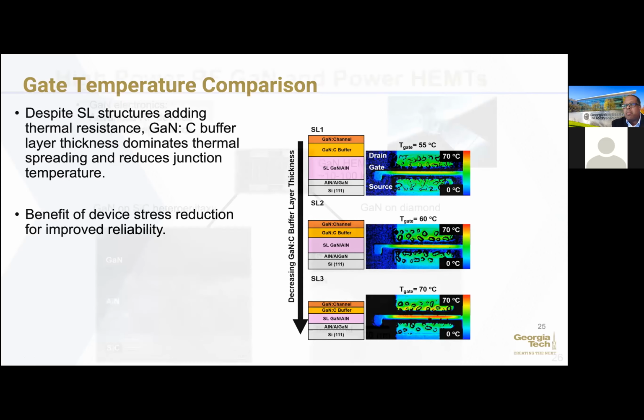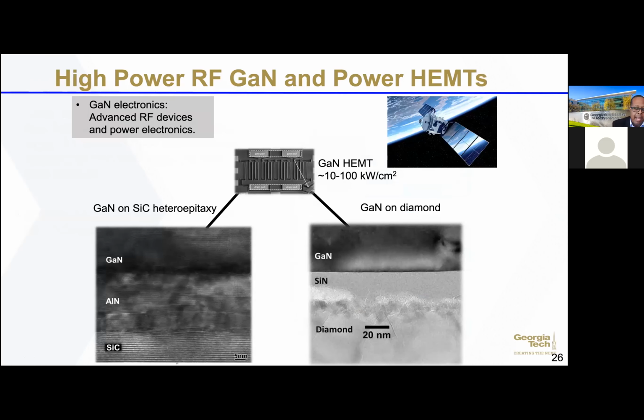Okay, so now I want to move on to something that's a little bit more high power, also challenging. So we're going to move to gallium nitride on silicon carbide, gallium nitride on diamond. And so again, what we talked about earlier was the need for this inner layer right here to help with the growth of high quality gallium nitride for electronic grade structures. And then if I were to move to GaN on diamond, again, we do this because I can go from a material that has a thermal conductivity of 400 watts per meter K to something here that's 2000 or higher, and so to help me dissipate the heat.